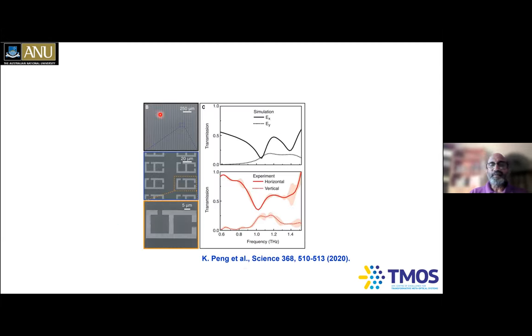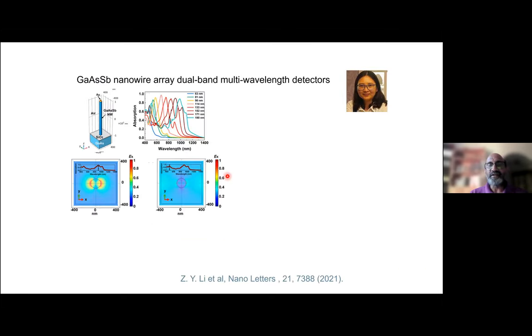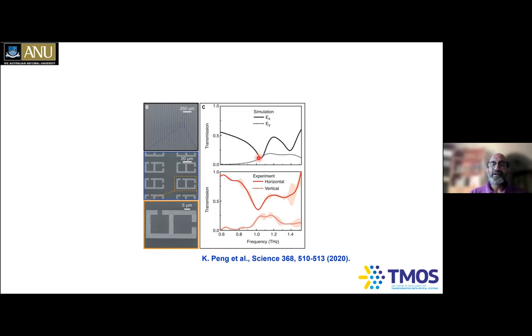So here's an example of these fabricated terahertz metamaterials. Kun Peng's simulations show that the X polarization, or the horizontal polarization, should have this particular shape of transmission through this particular structure. And then the vertical polarization, or Y polarization, should have this particular profile. And that's exactly what she measured using the detector, experimentally, both in X and Y polarizations here, for example.